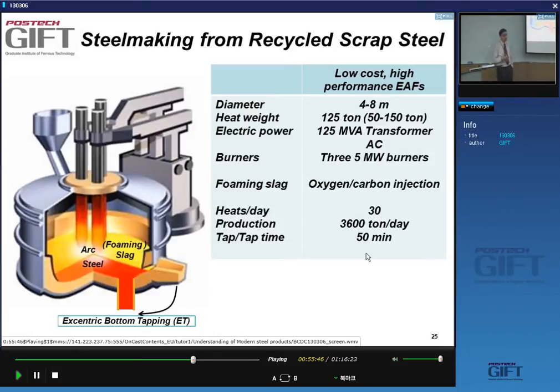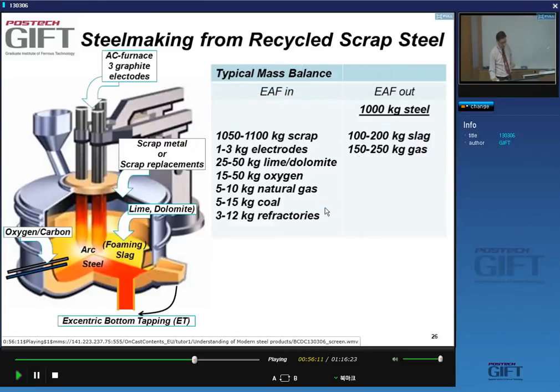So it's a route where the production rate is slightly lower than the blast furnace converter route. You can see here, in particular, the heats that you produce are smaller, and the tap-to-tap times are about twice the tap-to-tap time of a converter. So typically, we input scrap metal or scrap replacements. We put in lime and dolomite. Dolomite is similar to lime. It's a carbonate, but it contains magnesium oxide in addition to calcium oxide to form the slag. You get this slag to foam by injecting oxygen and carbon into it.